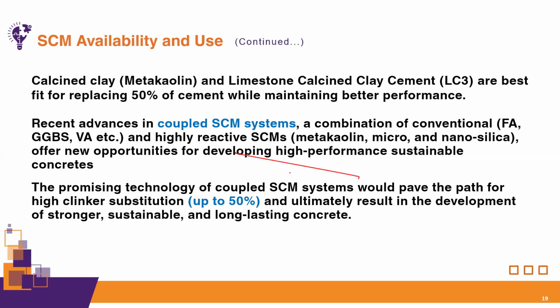So the target is to replace cement by 50%. This is the target in order to achieve the IEA roadmap. So you can see the calcined clay, which is also called metakaolin. The commercial name of this material is metakaolin. And limestone calcined clay cement, another type of cement which is called LC3, is the best fit for replacing 50% of the cement while also maintaining better performance.